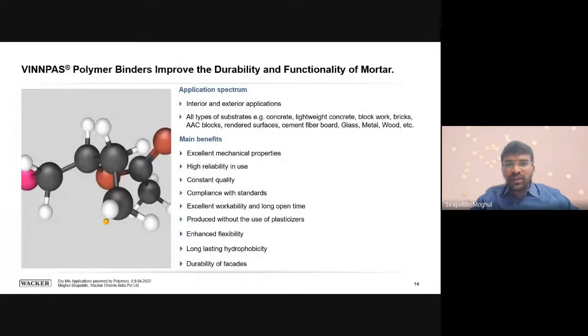And coming to the functionality of these polymers, it enhances the mechanical properties of the mortar, like flexural strength, which increases because polymer is flexible in nature. When we add polymer, it enhances the flexibility of the mortar and increases the workability, where you will be able to use the mortar for a long time, and you will not need any superplasticizers. And then it provides hydrophobicity, which is nothing but water repellency, which will remain for a long time, and it will improve the durability of the mortar. So there are many benefits.